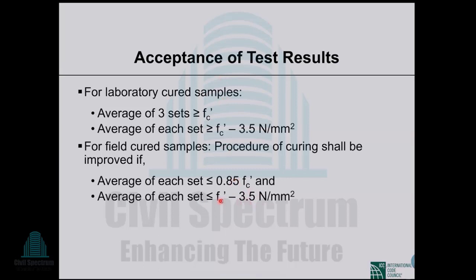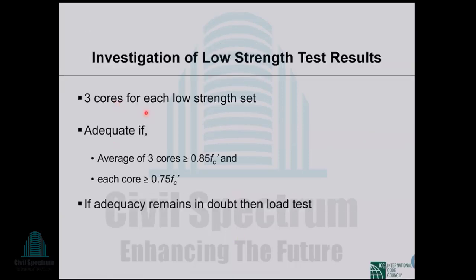So suppose your cylinders fail these criteria, what will happen? In that case, you have to take cores, 3 cores for each low strength set. You are collecting specimens from different parts. For example, if one set is made by 100 by 200 millimeter cylinders, you will have to cut 3 cores to represent the same concrete. So for each low strength set, you have to cut 3 cores and test the core samples.